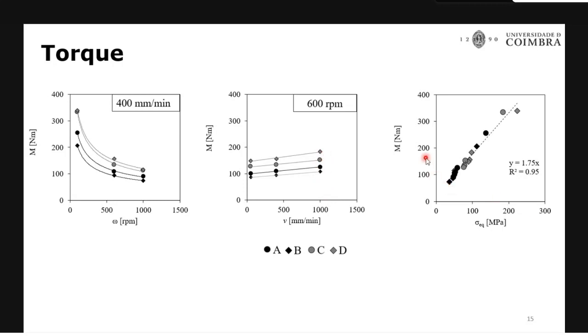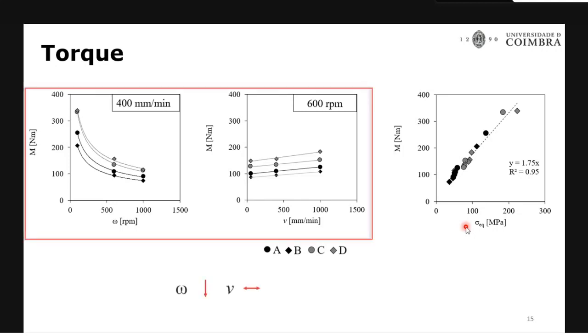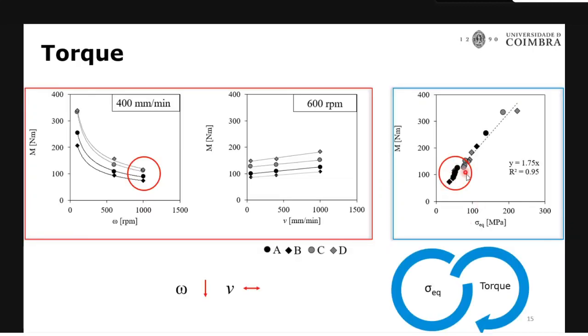When we plot the relationship between the torque and the flow strength, we find that there is a linear relationship. So the torque, or the defect formation, will be related to the flow strength. If you are going for a higher flow strength material, you will have a higher possibility of defects, and we can also say that you may have a lot of problems with tool damage. And these two have a relationship. Why does lower flow strength have lower torque? Because you have a higher rotational speed there, and you will have a higher temperature there. So everything is agreeing accordingly.